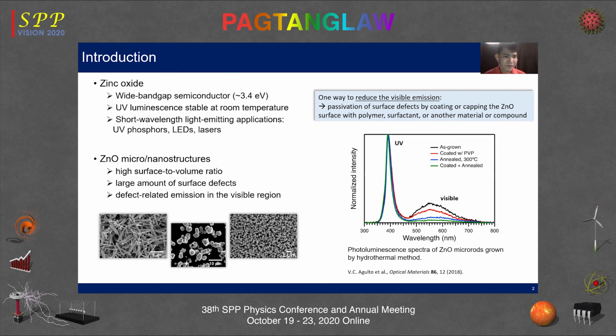Having a large surface area, ZnO micro to nanostructures have a generally large amount of surface defects, and this has a significant effect on its photoluminescence property, unlike in the case of bulk crystals. Surface defects can subsequently lead to non-radiative carrier relaxation or visible emission due to defect-related electronic transitions.